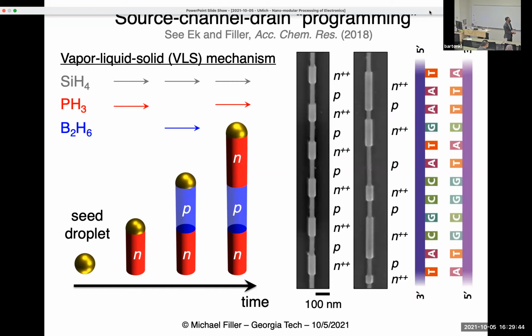So these are single crystal silicon wires with different dopant profiles. And the reason you see this diameter modulation is because we've etched the wire selectively in an etchant after the fact. If I showed you the wire immediately after growth, it'd just be kind of a solid structure, even though the dopants were in there. And here we're just resolving it for you so you can see the dopant profile. You can see the nanoscale control that we can achieve in structures like this. And I really think of it as like programming DNA. I mean, we can control, as you can see here, what kind of dopant we want to put in and for how long.